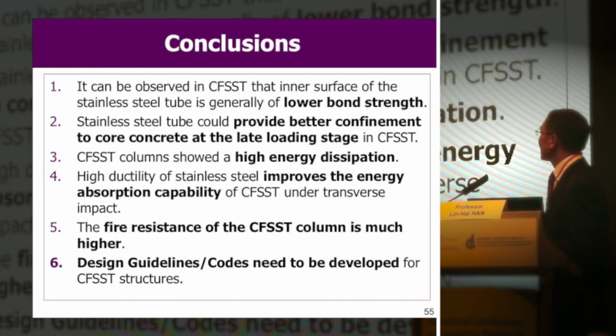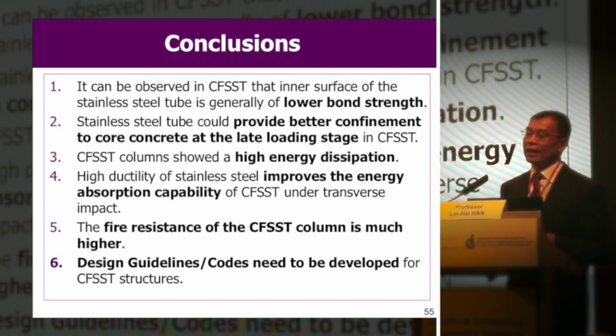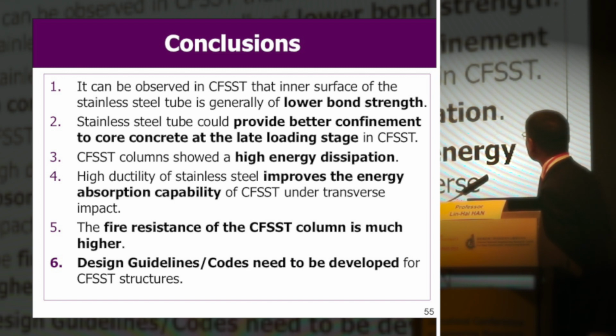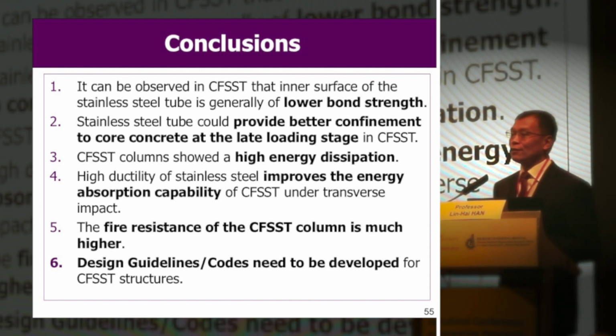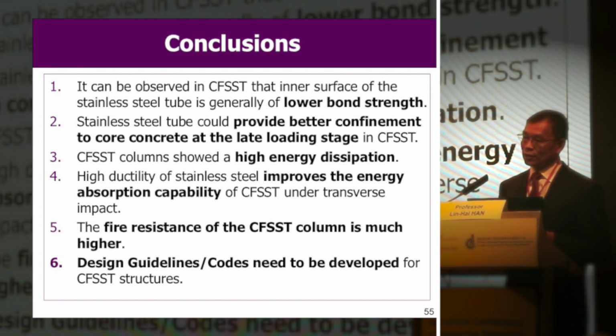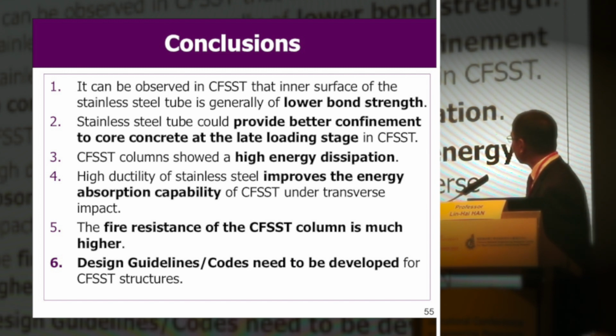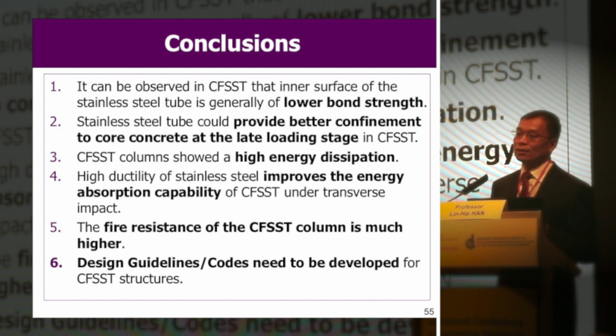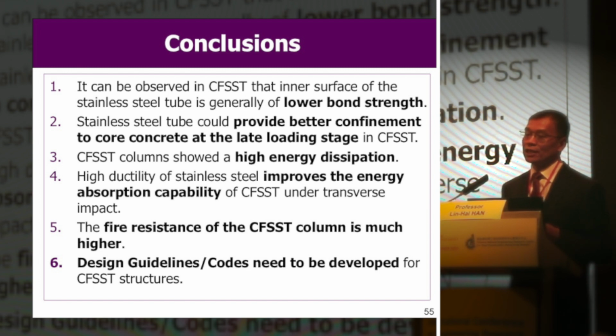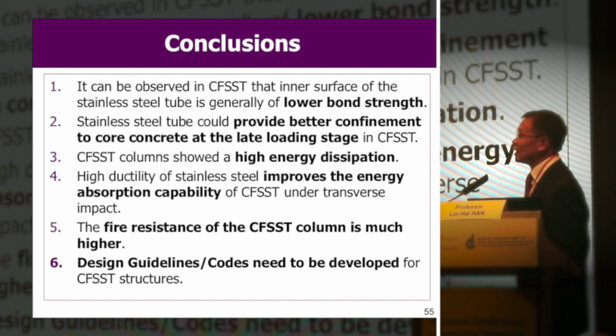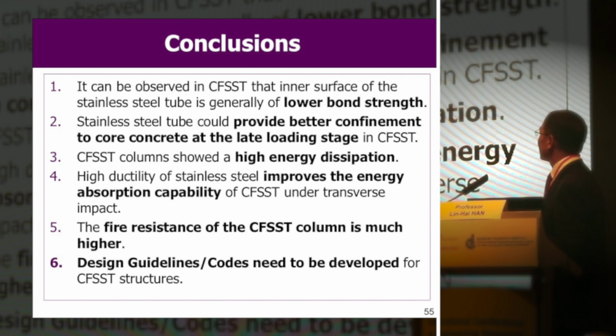In conclusion, it can be observed that the bond strength between the stainless steel tube and concrete is lower than that of normal carbon steel tube and concrete. So this is the issue. We have to face this issue and give a safe design bond strength. For larger specimens, for instance larger sections, we will need additional shear studs. This will give some proofs.